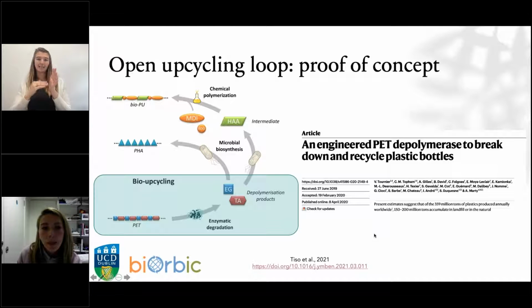and it's a very efficient process. What the authors of this paper showed was that you can extract ethylene glycol and terephthalic acid from this hydrolysate and make not virgin, but you can remake polyethylene terephthalate. What we're proposing to do here, as I said in the previous slide, is to directly use what you get from enzymatic hydrolysis to feed bacteria, and thereby circumvent the quite expensive process of extraction of ethylene glycol and terephthalic acid.